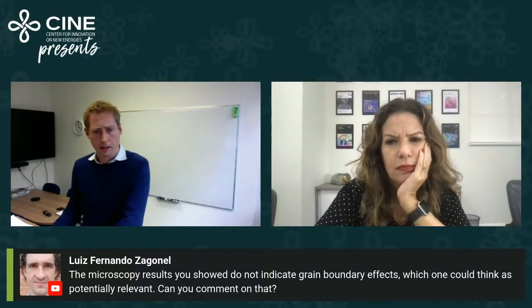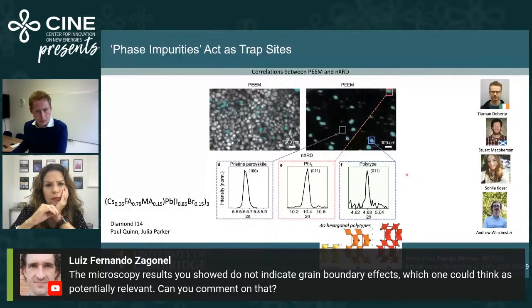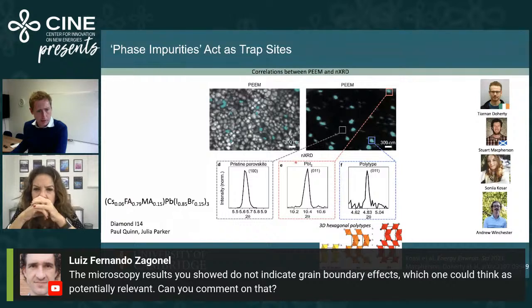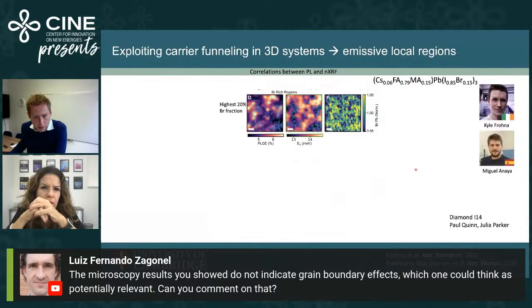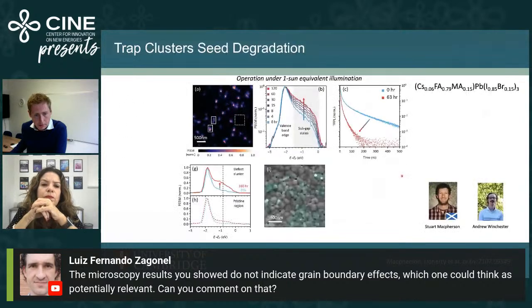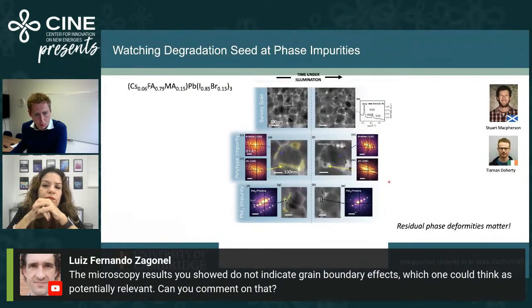So if we look at an example, I'm not sure if I have, oh, maybe I don't have a very good example here. When we look at the very high resolution measurements, we can see tiny little grain boundary features that sit at boundaries. And in fact, I may have, here's an example. So these are polytypes that are sitting at boundaries. They're little small phase inclusions that are problematic. And these are carrier traps, and these are also instability sites. So they do often tend to decorate grains and do sit at boundaries.